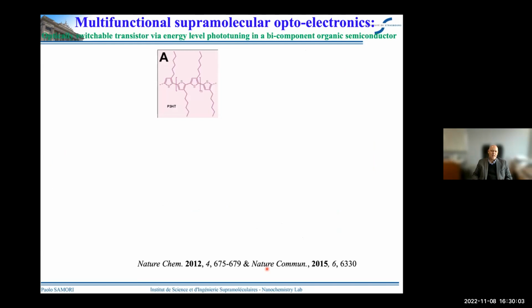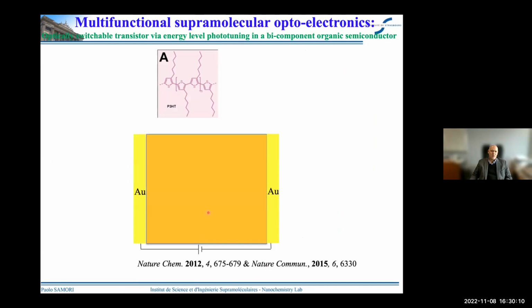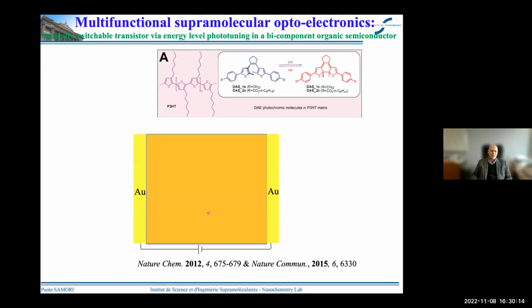You can fabricate a transistor based on pure P3HT, that is this material in orange in between the two gold electrodes. You can actually blend it with the diarylethene. And we have designed and synthesized, together with Stefan Hecht, some diarylethenes such that their HOMO level in the closed state is in the band gap of the P3HT, and in the open state is out of the band gap. Now, what does it mean when you have a dopant whose level is in the band gap of the semiconductor? When the level is within the band gap, the dopant will behave as a trap for the charge of the semiconductor. Whereas when it is out of the band gap, the interaction between the two is purely electrostatic.